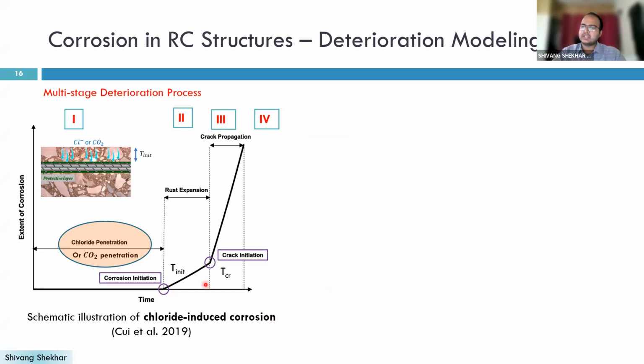You can see it here. I have tried to show that after some time the corrosion initiates. Once the corrosion initiates, here I am showing the initiation time. The rust forms and there is an expansion. That leads to cracking in the concrete, and with this, the extent of the corrosion increases. So stage 1, stage 2, stage 3, and stage 4. There are 4 stages of corrosion. First is the time till the initiation. Then from initiation time till the rust expansion and cracking of the concrete occur. And then the spalling of the concrete.